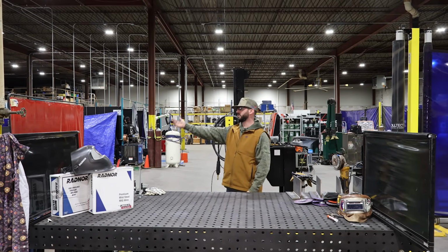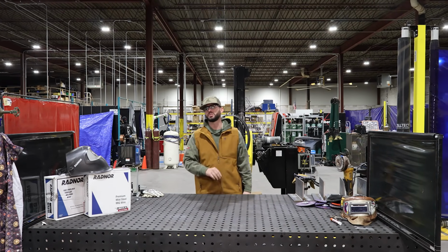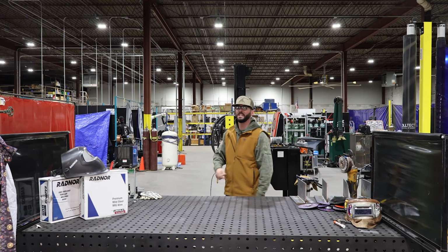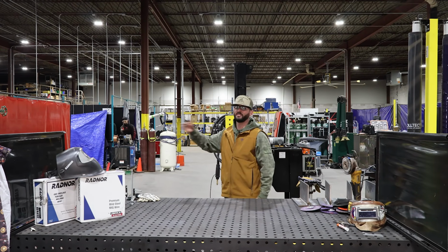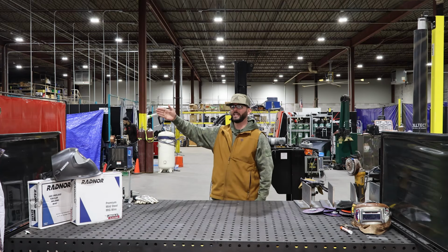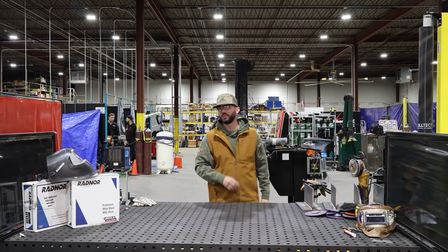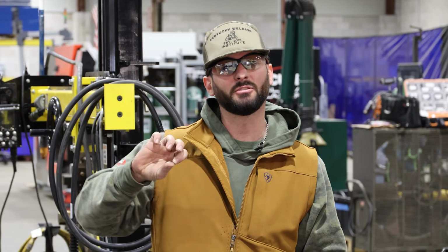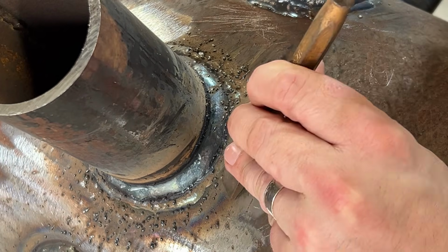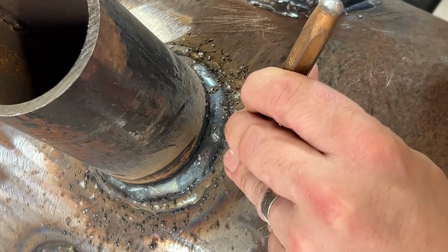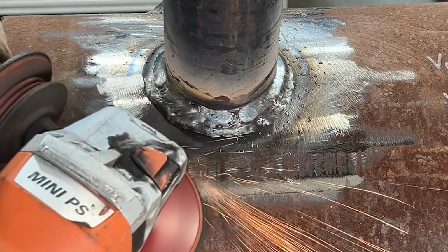You might have a breeze running through the bay door coming across your weld and giving you the occasional porosity, or your weld partner across the way has a fan blowing and it's oscillating. It eventually gets to yours and blows a little bit of your shielding gas away. Turning that flow rate up to a really high point is not going to be the solution, though. Too fast a flow rate coming out of your nozzle is going to cause a lot of turbulence in the puddle. Turbulence in the puddle typically causes a lot more spatter. So you're going to have what seems to be a much more violent puddle because that gas is blowing on it so aggressively.